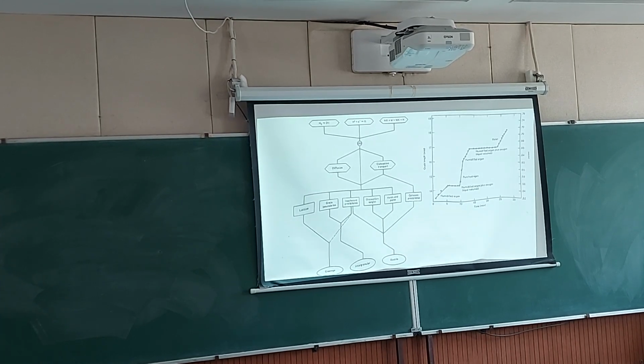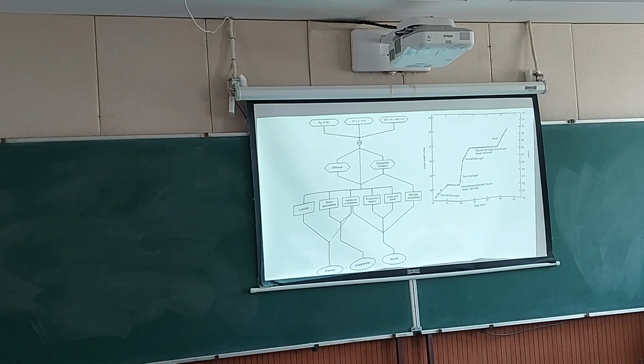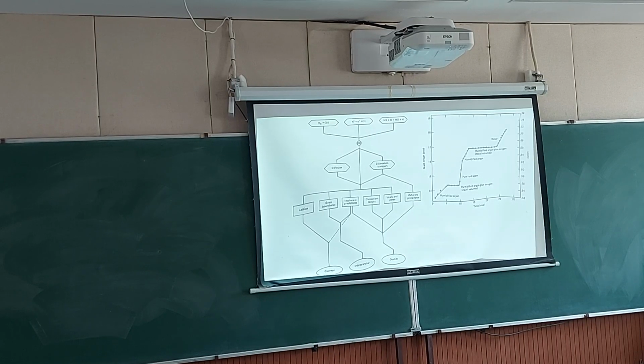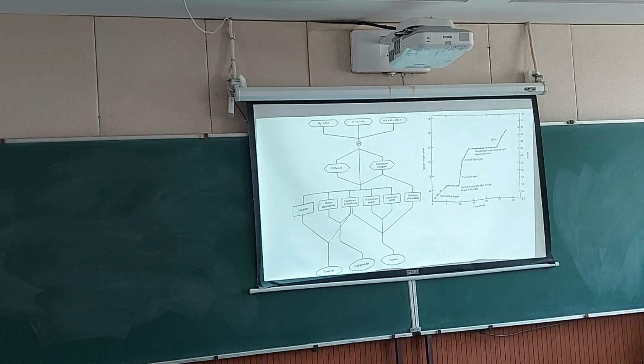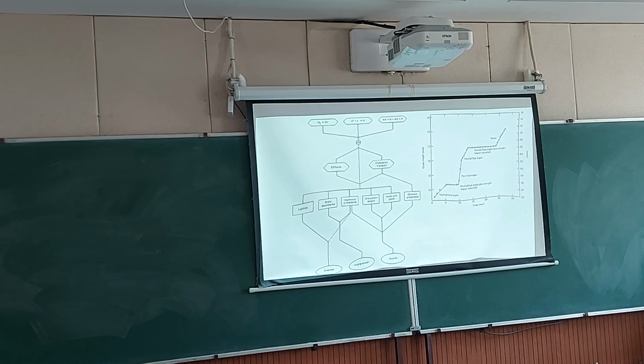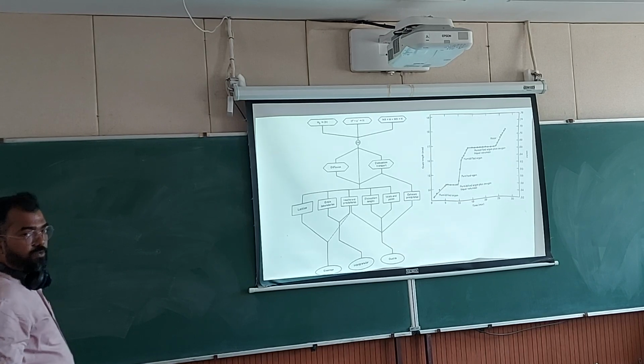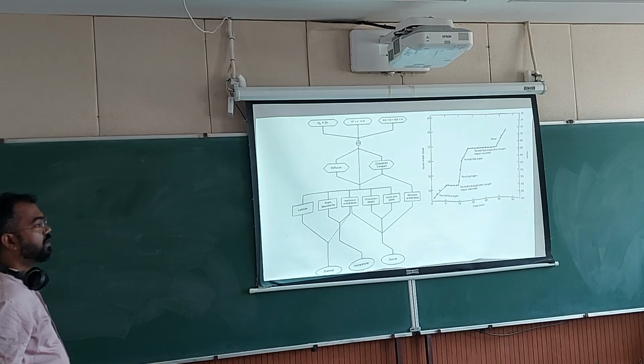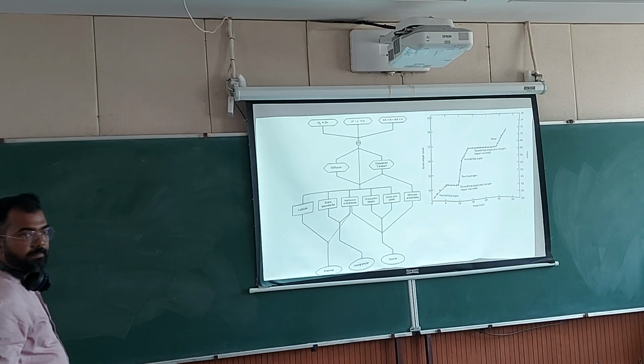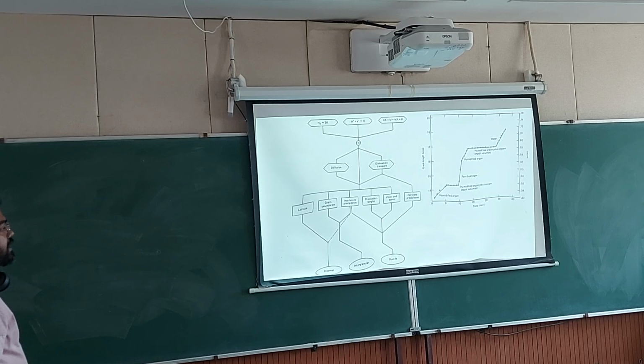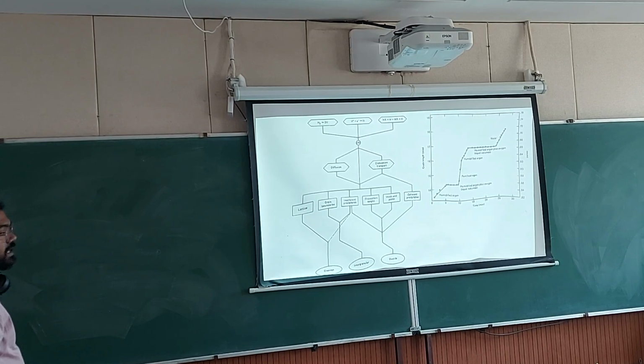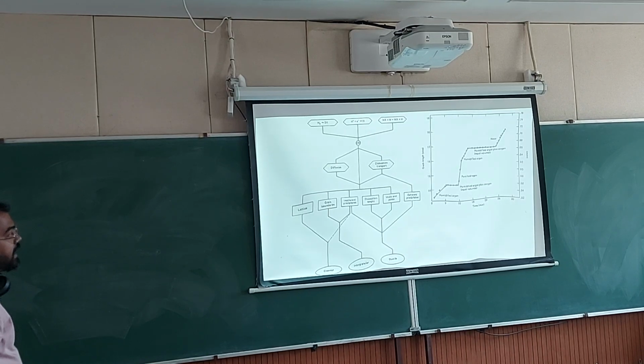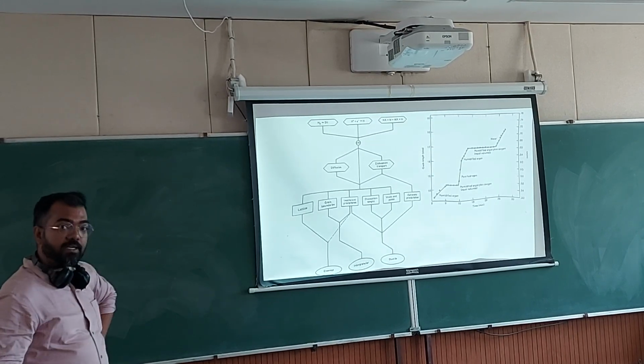It can react with a metal and it can form a metal salt with whatever anion hydrogen is combined with. So it can be H2O, it can be HCl, it can be H2SO4, all those things. So you can have metal sulfate, metal chloride and things like that formation, and hydrogen will be available. And then it can diffuse in the material or it can combine or assemble with the dislocations, and via those it can interact with the lattice by changing its shear modulus. It can go to the grain boundary, make hydrides. It can interact with the incoherent precipitate. It can form dislocation tangles. It can also generate dislocations.